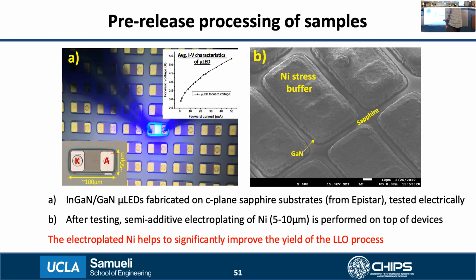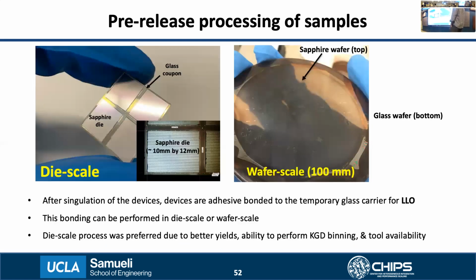On the right side is after performing the first steps of electroplating the nickel stress buffer layer on the device, and also dry etching or singulating the device by etching the InGaN/GaN between the devices to expose the sapphire. Once this has been done, the next step would be to bond these singulated devices to the temporary carrier, which is what can be seen in this slide, where we have done it in two scales: die scale and wafer scale.